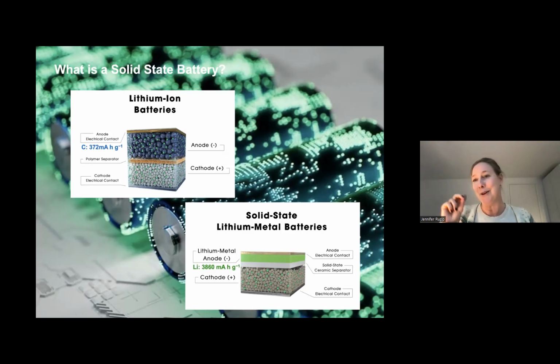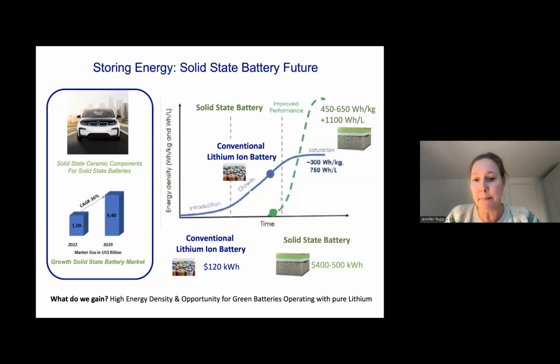Now, the really beautiful thing about a solid-state battery is that you replace the original polymer separator with a ceramic material. It's a ceramic that is stuffed with lithium. The lithium is encapsulated. And by having the ceramic material class as the electrolyte, you enable the use of pure lithium, which has a factor of 10 higher capacity compared to graphite. And on the cathode side, you can choose, for instance, a full cathode particle material, but it can still be a bit of a liquid, which would then be almost solid state. So there are different flavors of these batteries. But in a nutshell, in my personal view, solid-state batteries are fantastic.